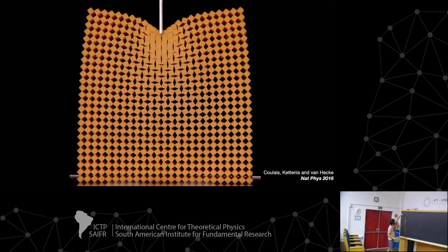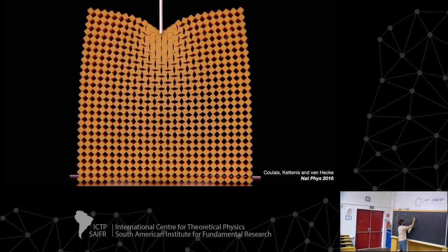So to do this, imagine I have a chain here, I push from here, that describes a column of the squares, right? Each is parameterized by an angle, theta 1, theta 2, theta 3, theta 4, and so on. One way in which you can describe this is through the energy. So you have a bending energy here that describes the sum of counter rotations, right? So when theta 1 and theta 2 move in the same direction, counterclockwise, the energy grows like this. But then you can also, for instance, have an extra shear energy. I put here a coefficient 1 for the torsional because I'm lazy.